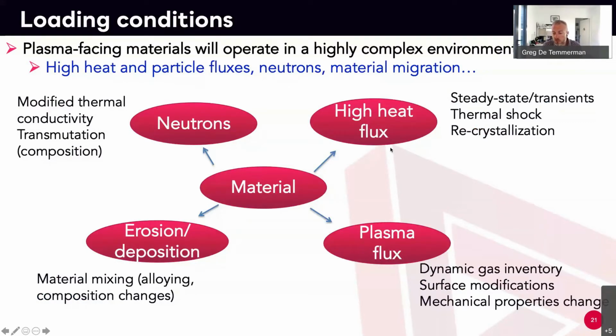It's also changing its composition. We have high heat fluxes, so I have to have a material which is resistant to high heat. I have the plasma particles, we'll talk about that. So continuously I'm putting particles inside the lattice of the material. So this is putting it under a lot of stress, and there are a lot of dynamic effects. And I have this issue of erosion and deposition. So the composition of the material will change because I have different materials around, and I will get a continuous mixing, which means I can have in some cases alloying. So I start with a pure material, but I end up with an alloy under a certain thickness, which is changing the parameters or the properties.